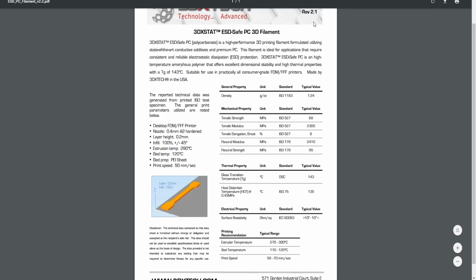And then quite a bit better glass transition temperature and heat distortion temperature. But you have to have 120 bed, and again 290 C print temperature or 270 C minimum. So I think that if you go with the polycarbonate ABS or the polycarbonate ASA, it's way better to pick that over the ESD polycarbonate. Again, one of the main reasons to get the ESD safe polycarbonate is if you're doing electronics housings and you don't want to have any sort of conduction through your filament to basically ground or to short out your electronics. So this main use is going to be for printing electronics housings.